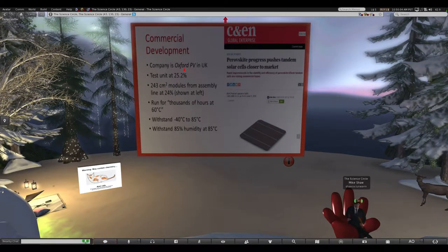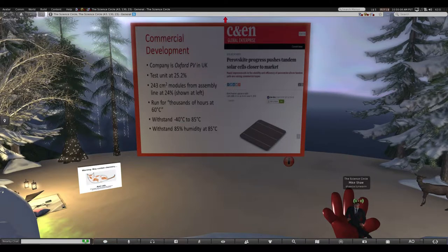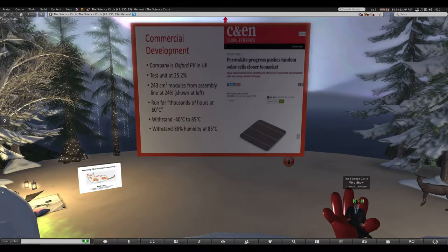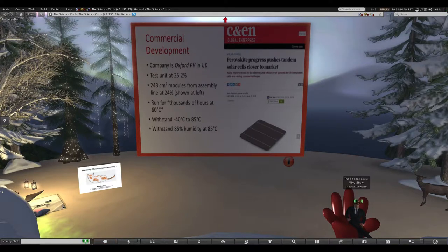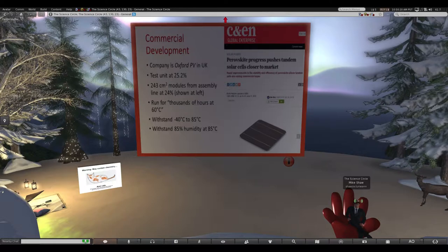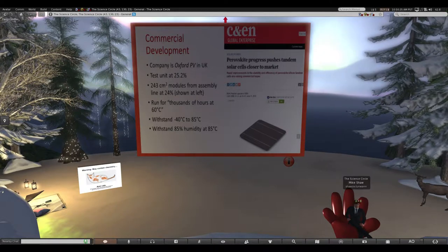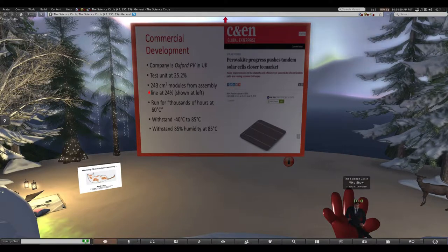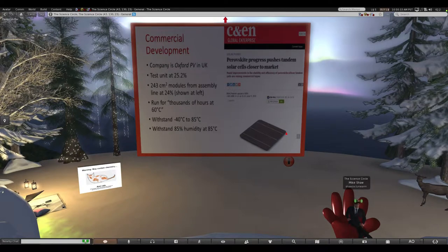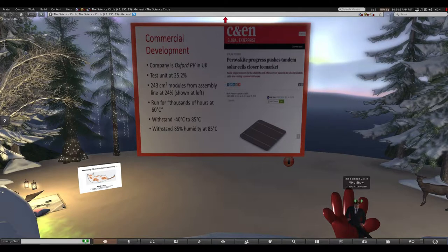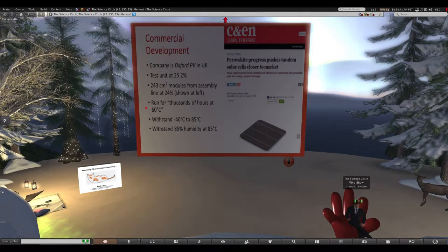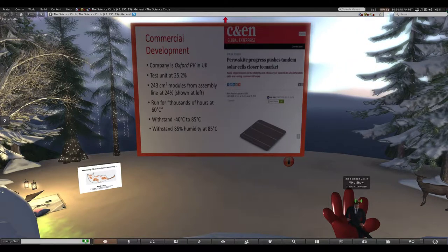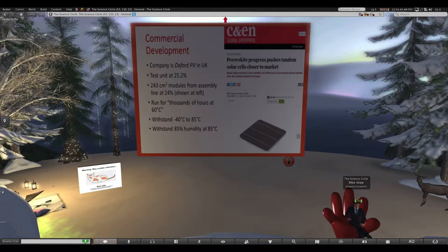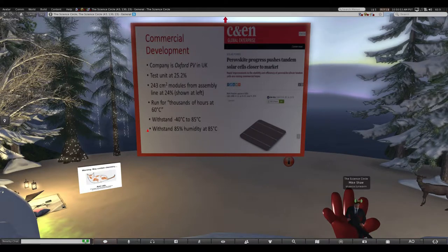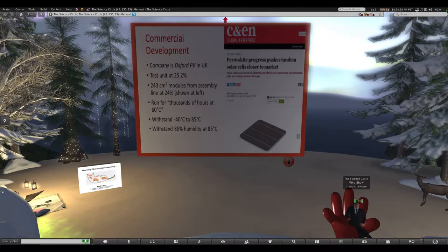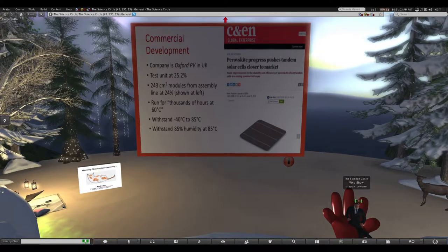At this time, Oxford PV, it's a spin-off from Oxford University, their test unit they demonstrated recently was actually, this is the current issue of C&EN News, so that's this week. The test unit was at 25.2%, very comparable to solar cells from silicon. The units that they've made off of their test assembly line, 243 square centimeters, are at 24% efficiency. And we've now got them running for, quote, thousands of hours at 60 degrees Celsius. And they actually withstand minus 40 up to 85 degrees Celsius. And they even withstand 85% humidity at 85 degrees Celsius. So these coatings are actually lasting very well.